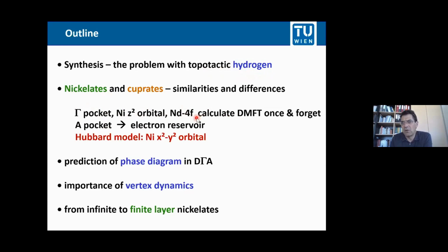But we did correlated calculations with dynamical mean field theory. And all of these orbitals are there in DFT, but in the superconducting doping regime, I will show you that you can calculate what they do, but they are not important. You can calculate them once and then forget about them. What is not going away is the A pocket. That is important as an electron reservoir.